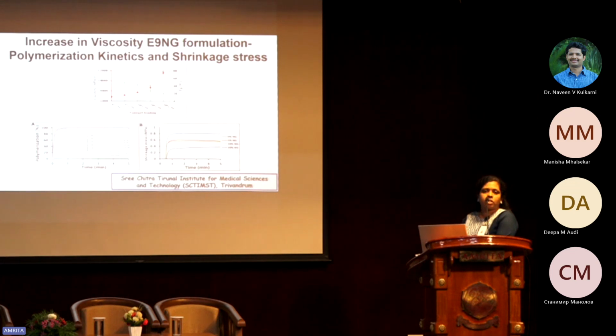And we also check the shrinkage stress of the system. Shrinkage stress is what happens when we are polymerizing a monomer. If we are going for free radical polymerization, since it is a very fast polymerization technique, it will introduce shrinkage stress, and also volumetric shrinkage will happen. That is not good for many applications, especially dental applications. So we check the shrinkage stress before and after adding the nanogel. We can see that the shrinkage stress is reducing as the nanogel composition of the system is increasing. So that is a very good thing. It's very useful in many applications, especially in dentistry.